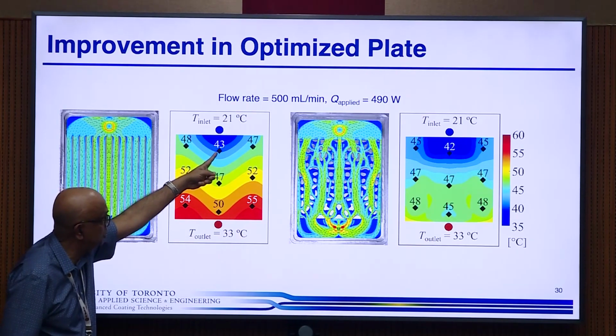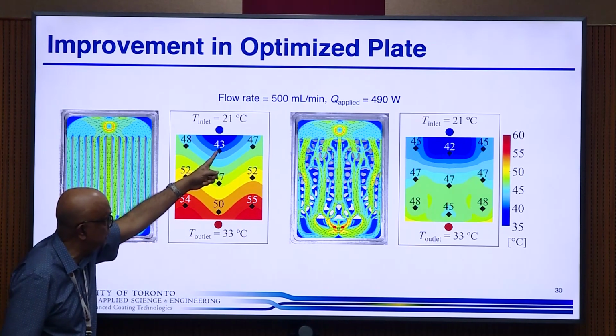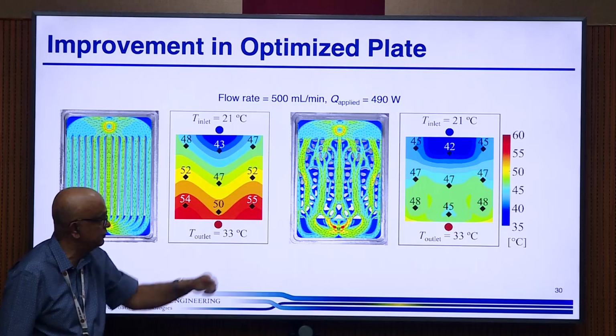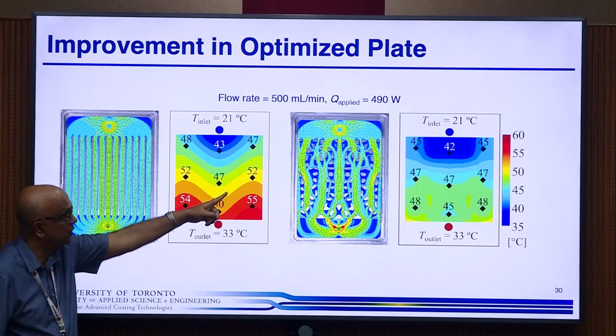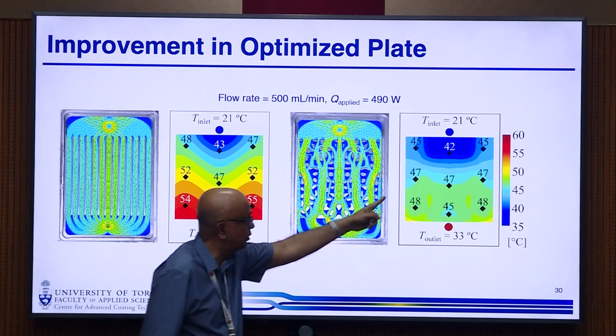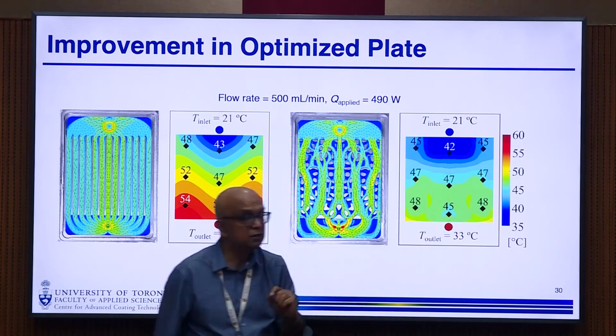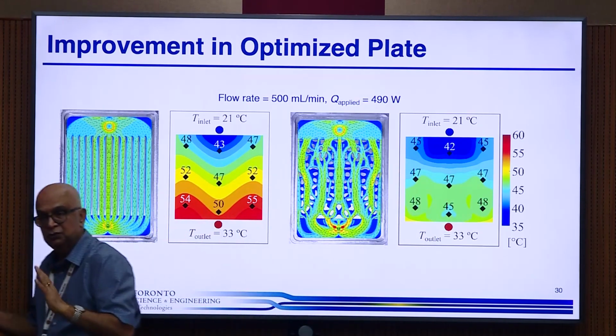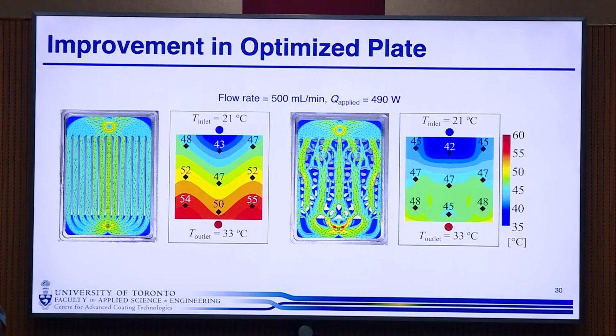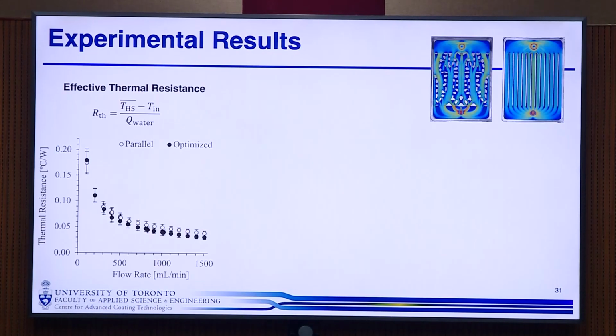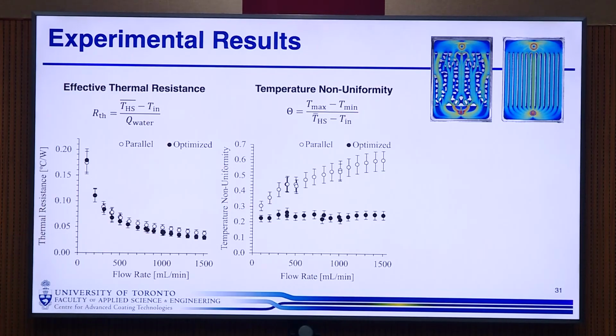And if you see, the temperature on the heat sink varies from 43 all the way to 55. With that one, we are going from 42 just to 48. So we've actually reduced the temperature difference significantly. Okay, so we can compare the thermal resistance for the parallel and the optimized, and they're a little better, not a whole lot better. But this is what we are really looking for.